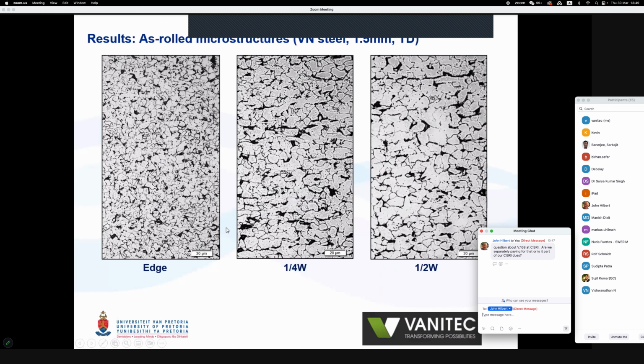This is what the microstructure typically looks like across the width of VN steel, a thin, 1.5 millimeter thick strip. You'll notice a very fine grain towards the edge, in the region of about 3 microns. It's transformed from fully recrystallized austenite. Then towards the quarter width and the mid width, we have grain size in the region of 6.5 microns.